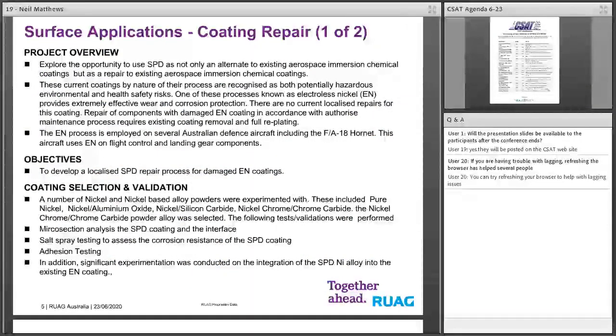The other area that we've been playing with is to basically see if we could develop repairs to some of the, let's say, more exotic coatings, particularly electroless nickel. That's a particularly difficult one to repair. What we've been doing there is to look at opportunities to do localized repair. The current repair strategy is that you've got to strip the e-nickel off and replate, and that's a long process.